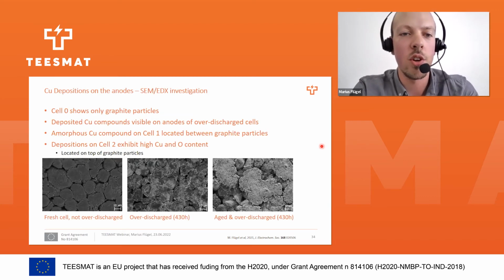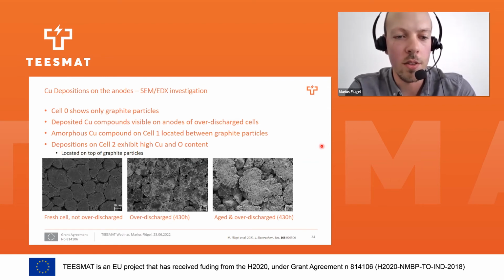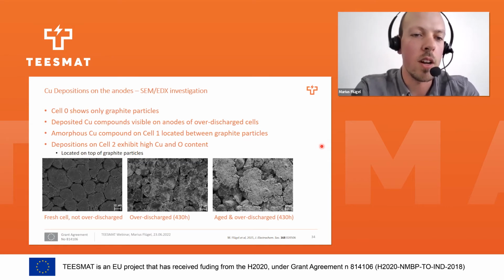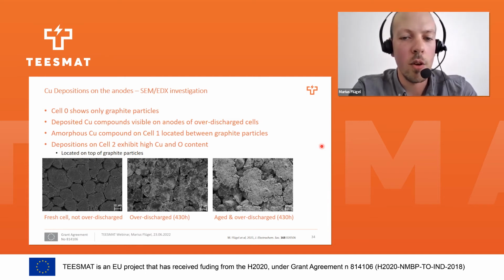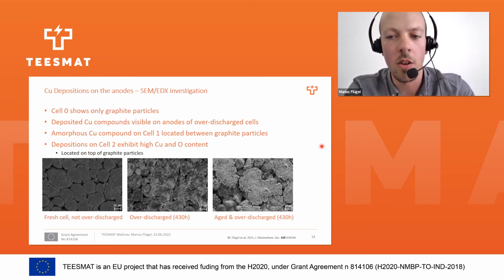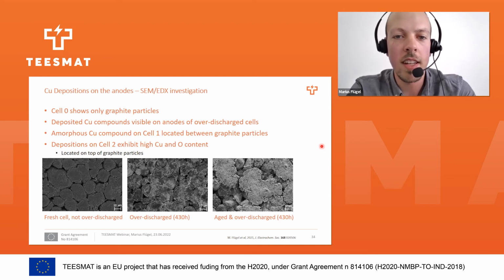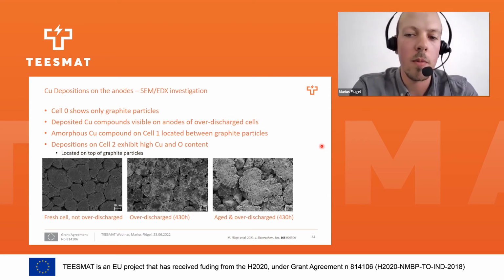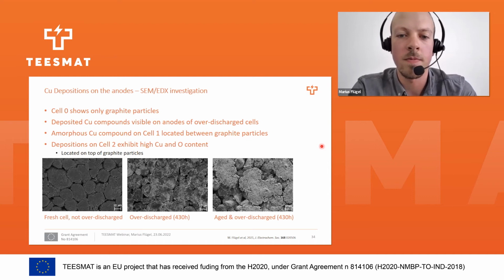SEM images showed that the pristine electrode, the fresh one which was not over-discharged, showed graphite particles, but no additional compounds. For the cell that was over-discharged without previous aging, we saw a compound which was located between the graphite particles, and EDX confirmed that it contained copper. For the cell that was previously aged at 0 degrees and then over-discharged, we saw a much higher amount of copper, which was this time located on top of the graphite particles.